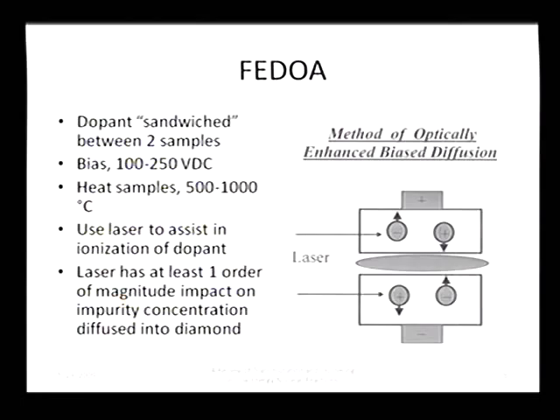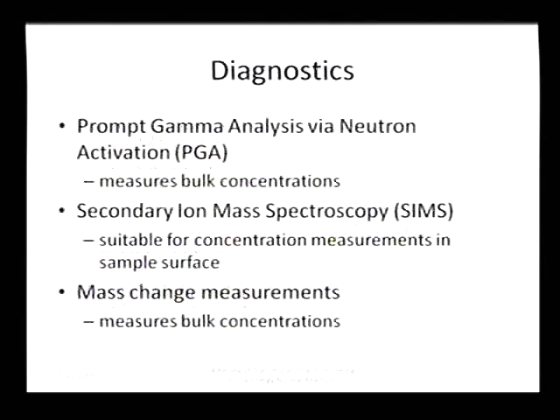And we also utilize a laser. The reason for the laser is that the ion inside of the diamond sample, once it's in solution with the solid, essentially is perpetually in an ionic state with the presence of the laser. Otherwise, it recombines, so the laser extends the lifetime of that ion considerably. The technique has been used to dope our diamond samples with various materials. We basically developed it to try to make N-type diamond, but we use this technique specifically to look at hydrogen loading.